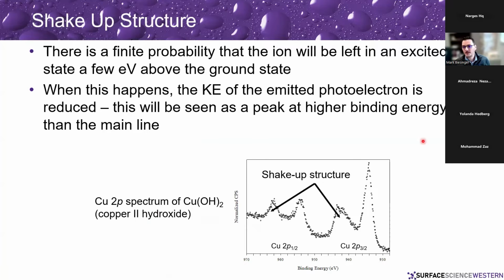Shake-up structures. There can be a finite probability that the ion will be left in an excited state a few eV above the ground state. And when this happens, the kinetic energy of the emitted photoelectrons is then reduced. And this will be seen as peaks at higher binding energies above the main line.